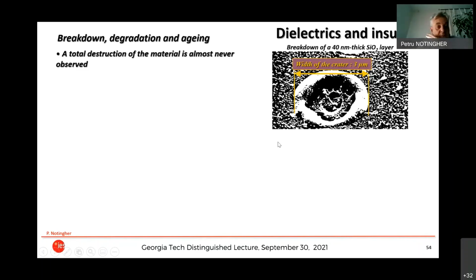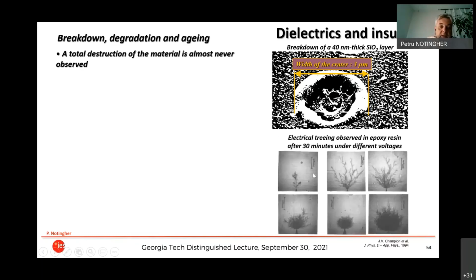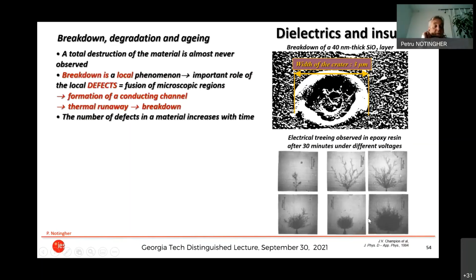A total destruction of the material is almost never observed. If you look at this picture, you see that the crater of the breakdown of a SiO2 layer is only 3 microns. So there is a small hole. It's not the entire surface of the film. Here there is another example with the thick insulator where electrical trees have developed. The length of the trees will increase with the voltage. So breakdown is a local phenomenon, and this is a very important thing to understand.